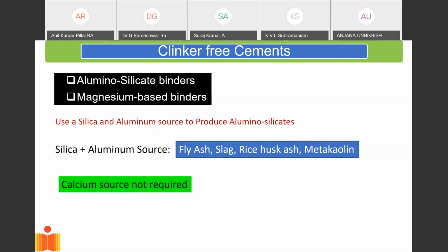The alternate forms that we're looking at are alumino-silicate based. So basically these don't rely on calcium as their base for strength, but they rely on alumina as their base of cement. And if you recall, fly ash had a good percentage of alumina in it. So therefore, now I can start making these binders or these cements using only fly ash, and that is the beauty of these alumino-silicate binders.